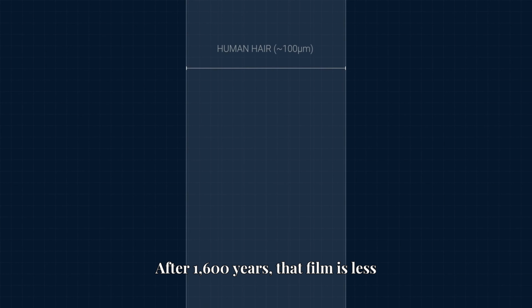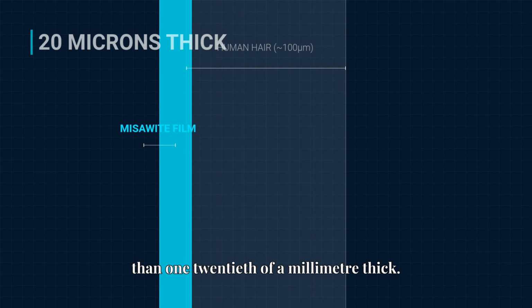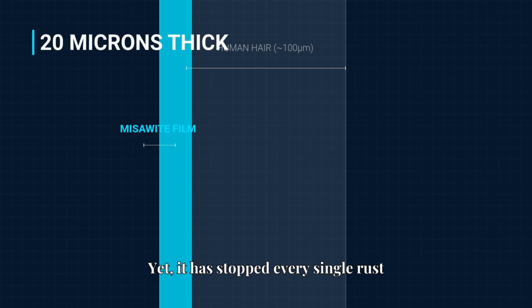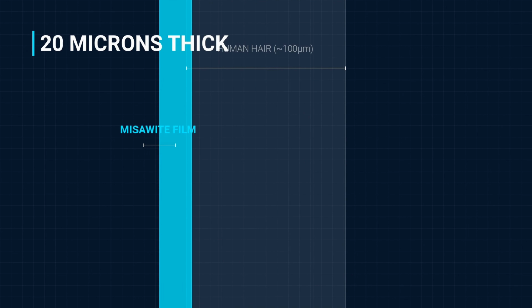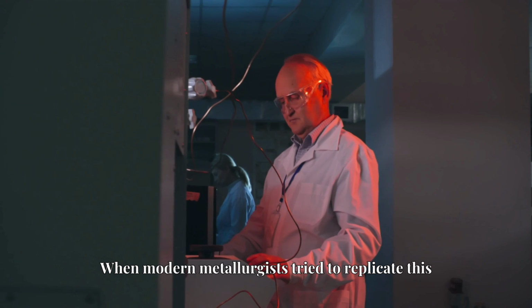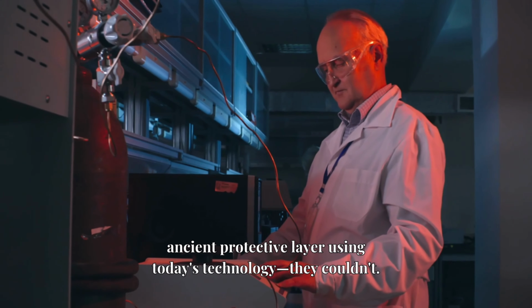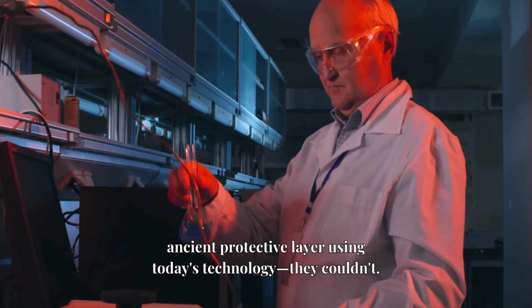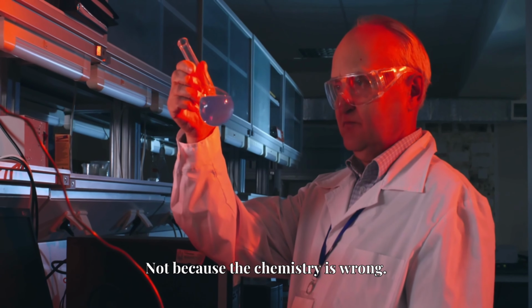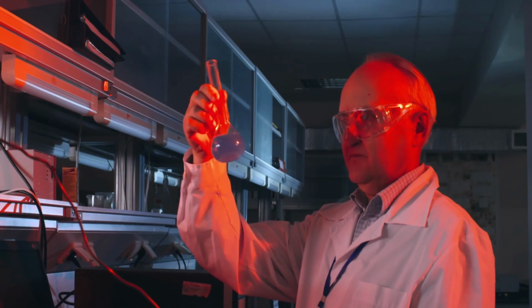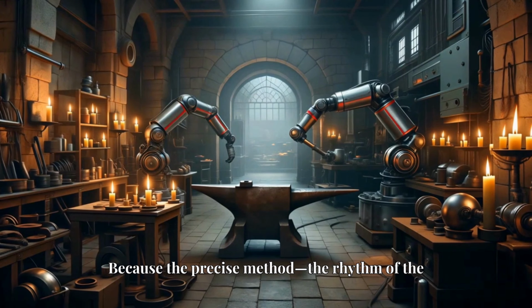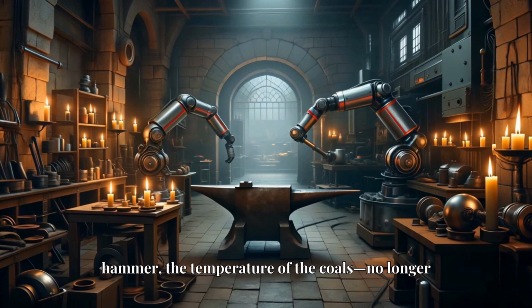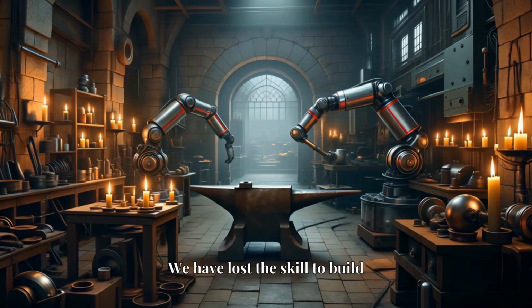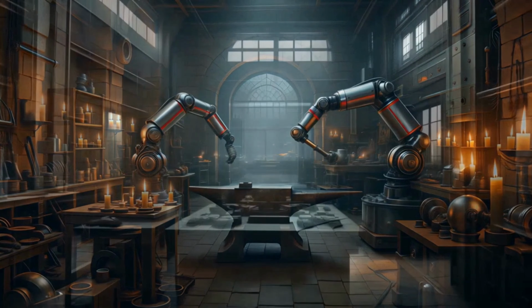After 1,600 years, that film is less than 1/50th of a millimeter thick. Yet, it has stopped every single rust reaction in its path. When modern metallurgists tried to replicate this ancient protective layer using today's technology, they couldn't. Not because the chemistry is wrong, because the precise method, the rhythm of the hammer, the temperature of the coals, no longer exists. We have lost the skill to build for eternity.